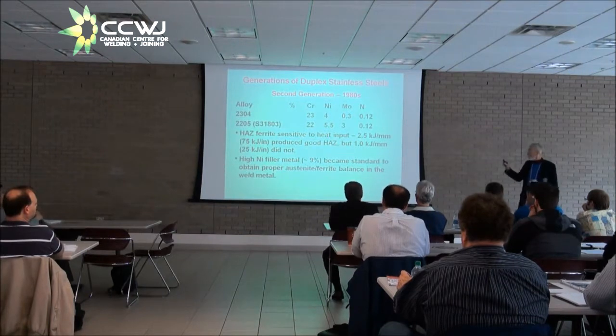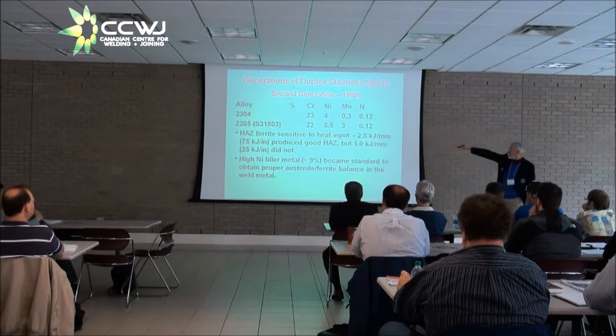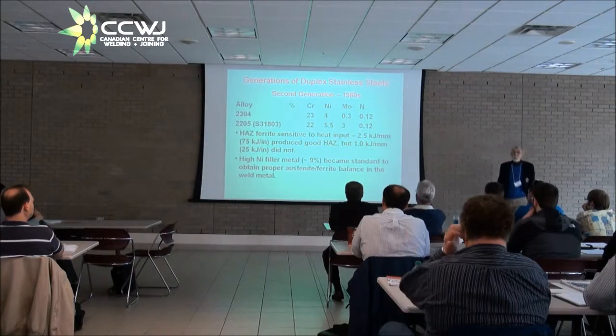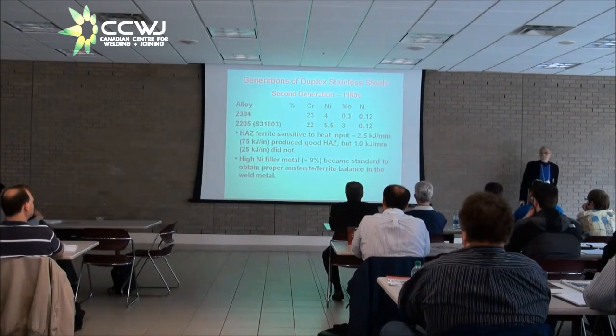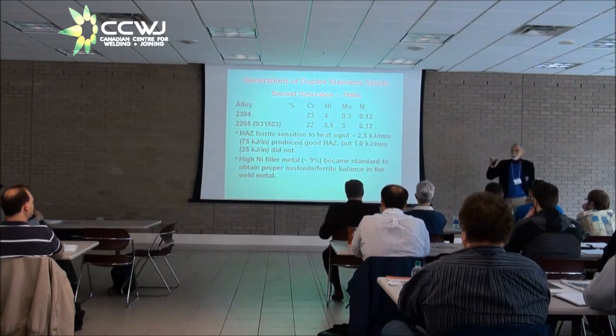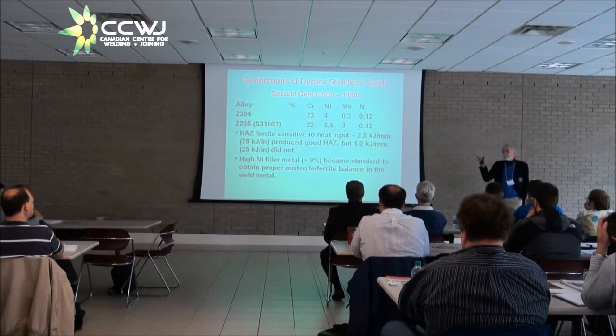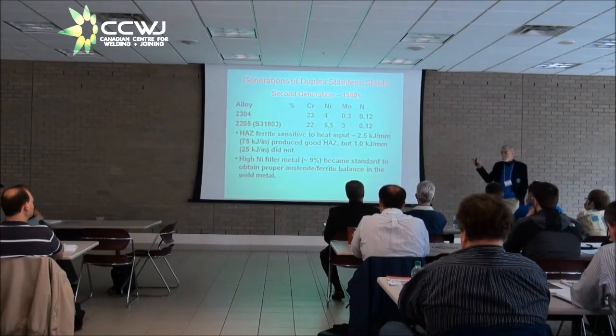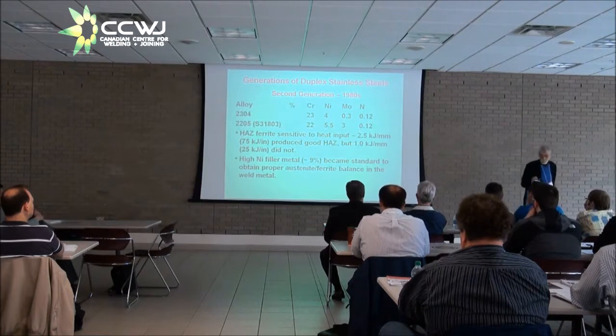Now, I want to point out one thing here. 2205 in the literature was always associated with UNS number S31803. And that's very important because it allowed for a rather low minimum nitrogen content, 0.08% minimum nitrogen, in order to satisfy UNS S31803.